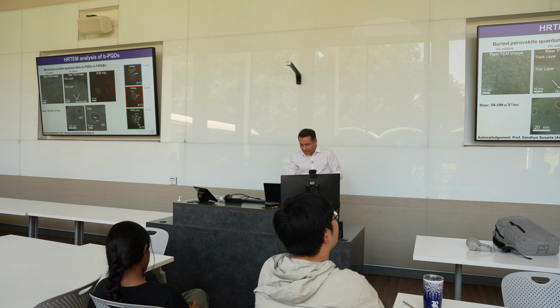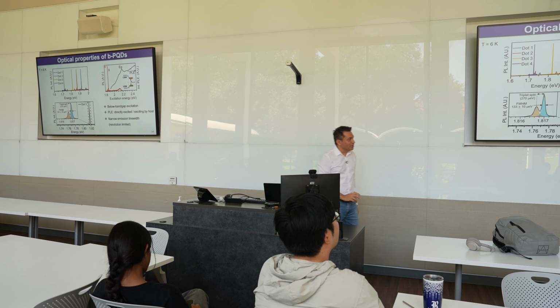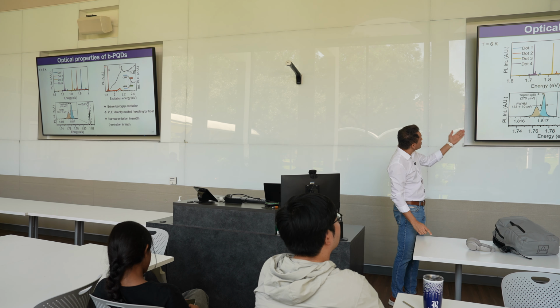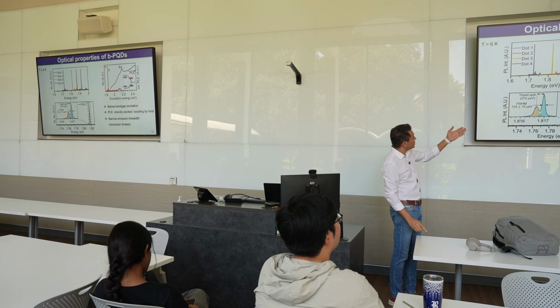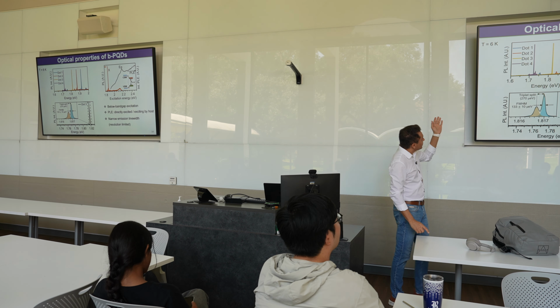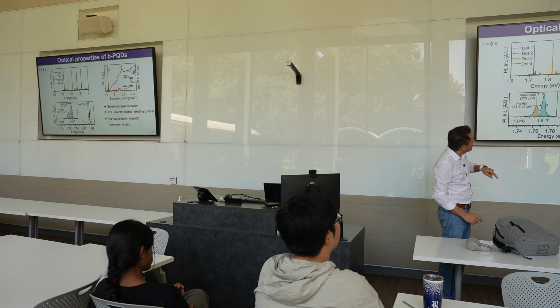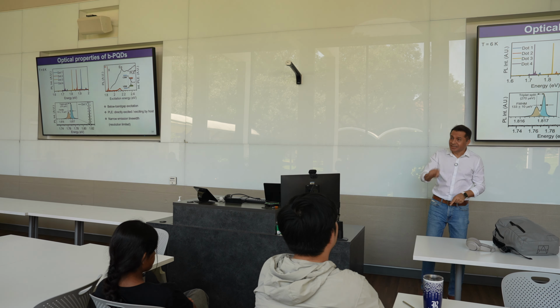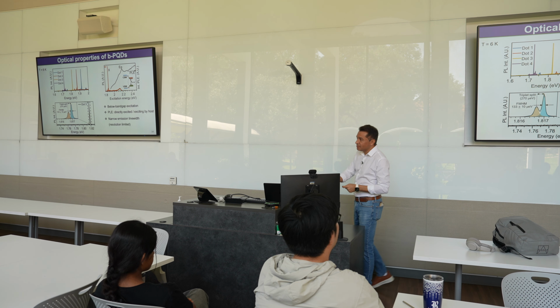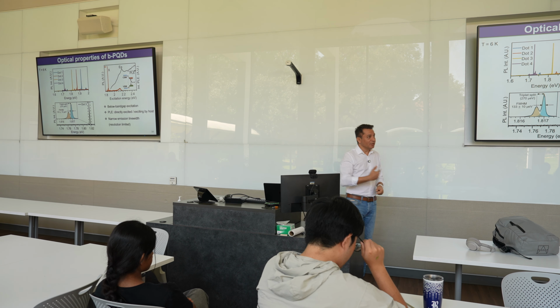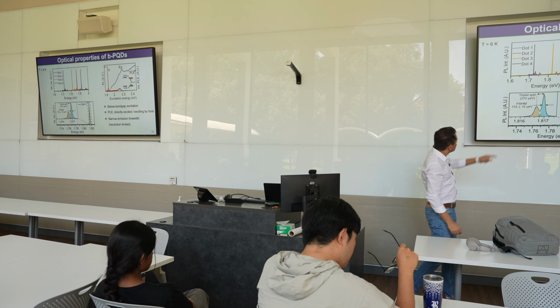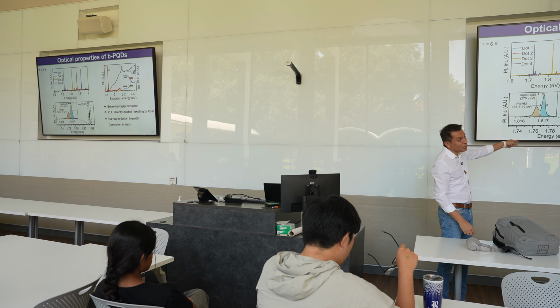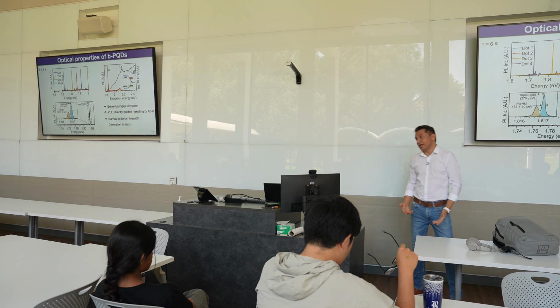And so you see a lot of emitters. They have different energies. So this is what you'll see: these are 4 dots in a single sample, and that's what it looks like. You can excite that dot locally. You can go below the band gap, excite the dot, look at the dynamics, and look at this. This is about 133 micro eV. That's the best we can do.